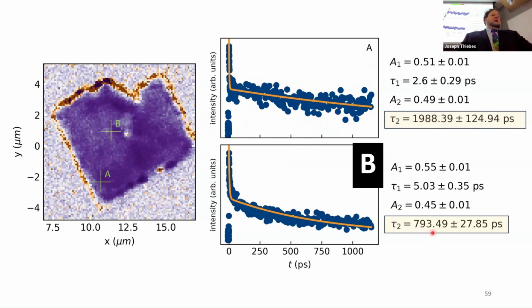And this wasn't just one set of data. I looked at a bunch of these measurements and thought, well, how do they compare at other edges, and looked at different crystals. And I kept seeing that there were much longer lifetimes at the edge than there were in the interior. And that would go along with having separated charges, because if they're separated, it's harder for them to recombine. And so they won't do it as often. And so you'll have longer lifetimes.